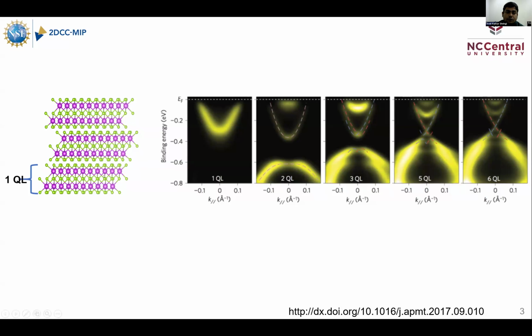The atomic structure shows quintuple-layer-thick bismuth chalcogenide, with van der Waals force between each quintuple layer, so they are 2D materials. They can be exfoliated down to one quintuple layer, and the image shows the direct Dirac cone separation at the lower quintuple layers. As we increase the thickness of bismuth chalcogenide, the band gap merges and forms a direct Dirac cone.